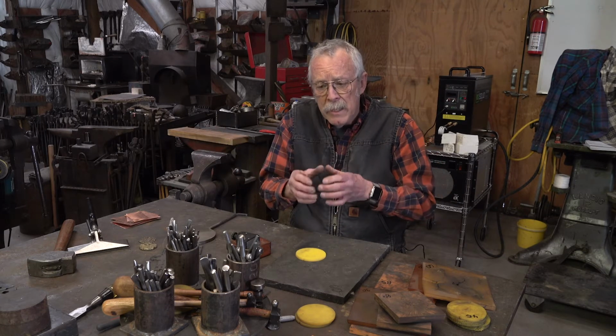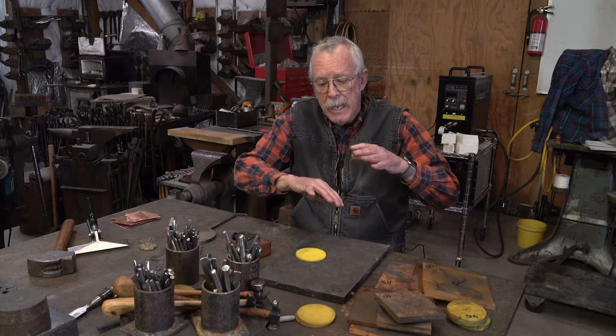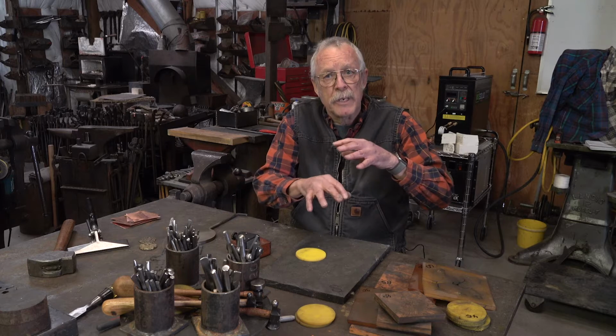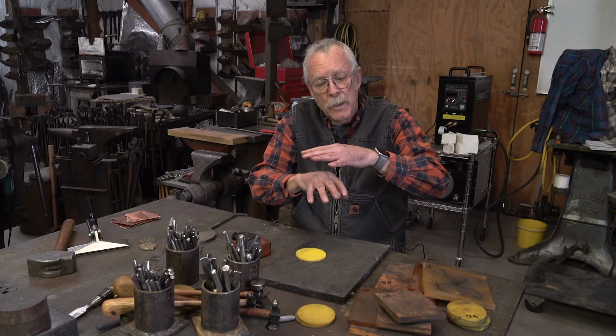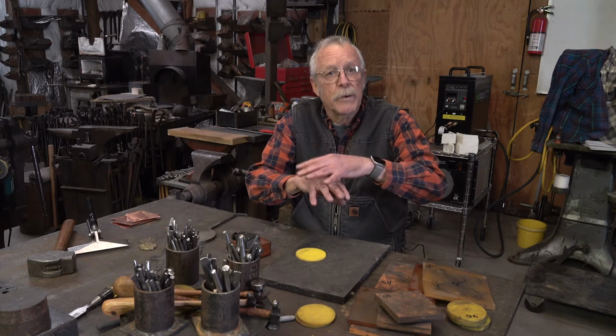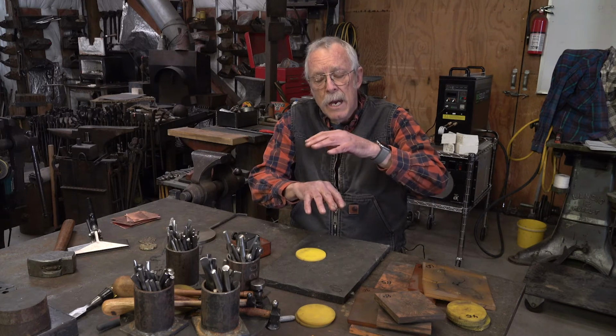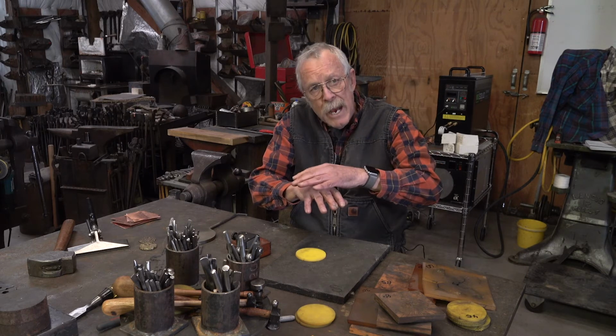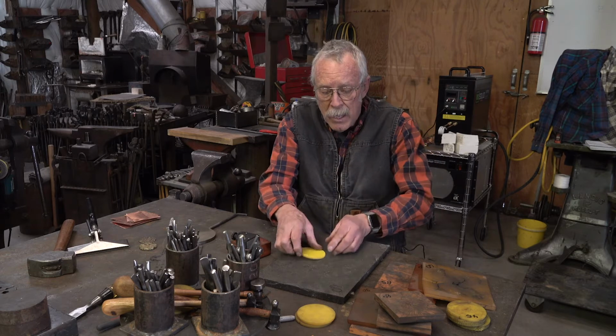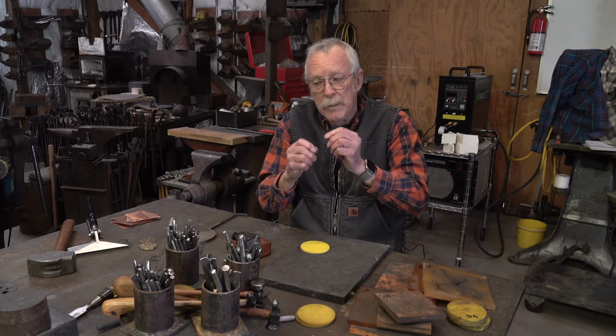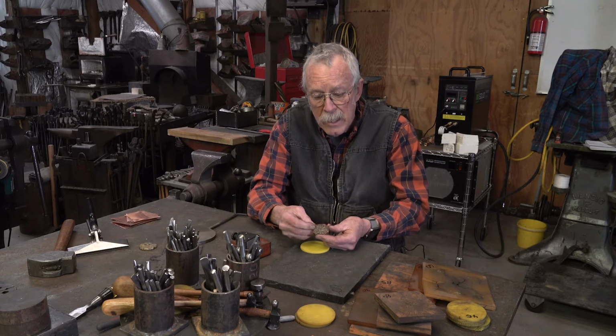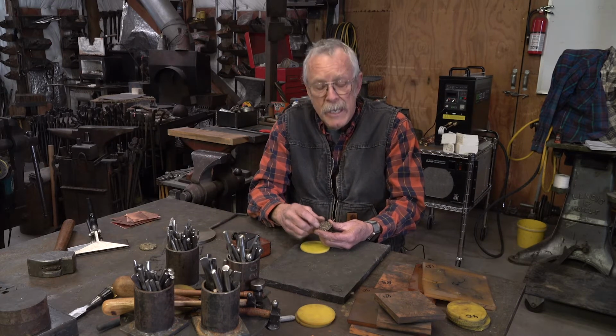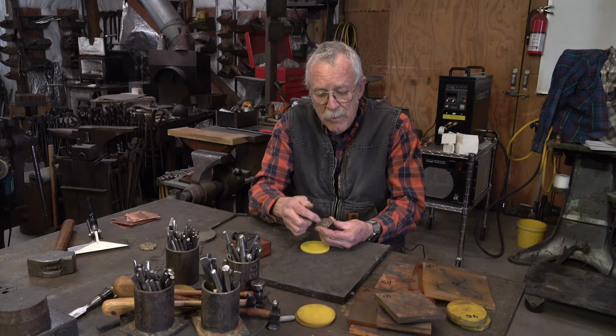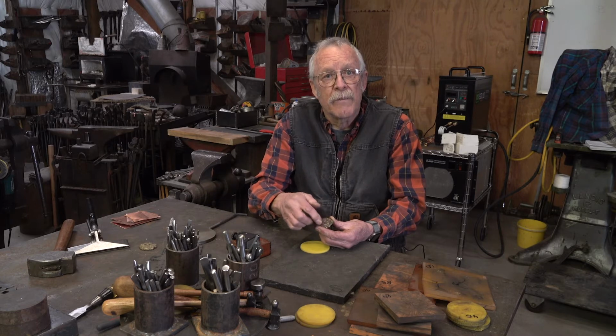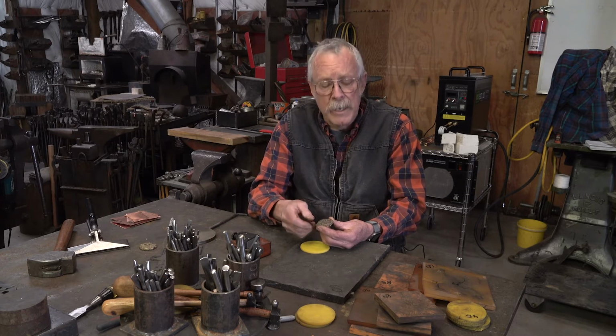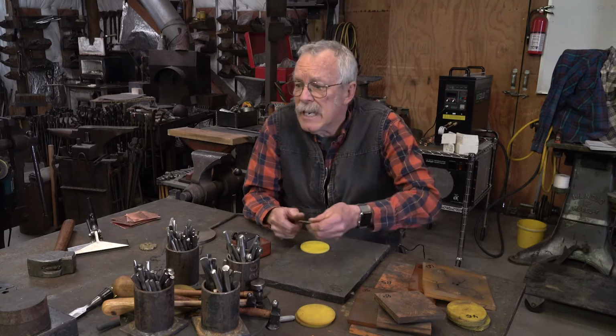But because of the displacement, if you put a shape underneath that has hollows in it in detail and then put a piece of annealed copper or sterling or whatever metal you want over it, when you push down on it, the polyurethane tries to go into the voids on whatever you're doing. Like in here, it would push into these voids instead of compressing. So as it pushes into the voids, it forces the copper into the voids where the copper's not supported. And it's amazing the detail you get.